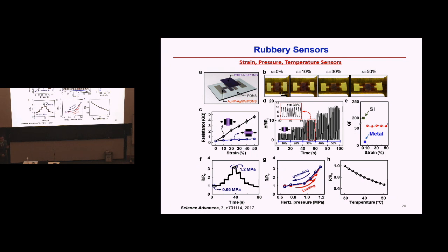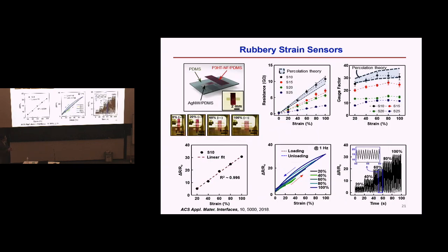In our first generation of semiconductor material, we have achieved a gauge factor of about 30, fairly linear over the range of 50%, which is very important for sensor technology. And by further optimizing this material, we can even achieve a range of more than 100%.